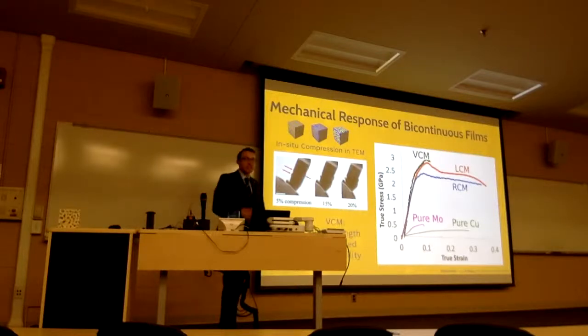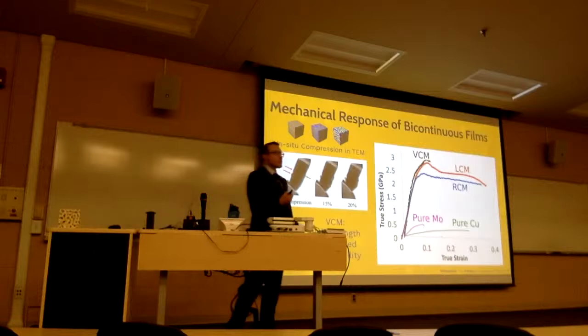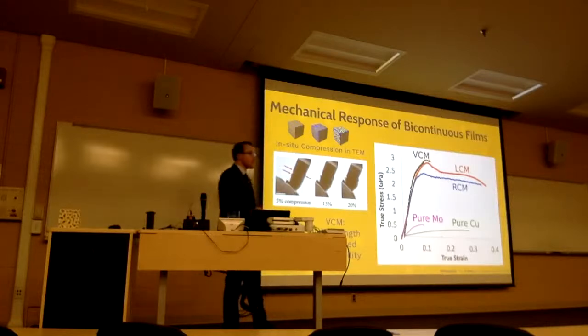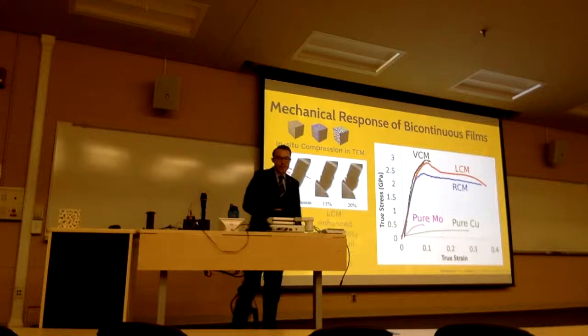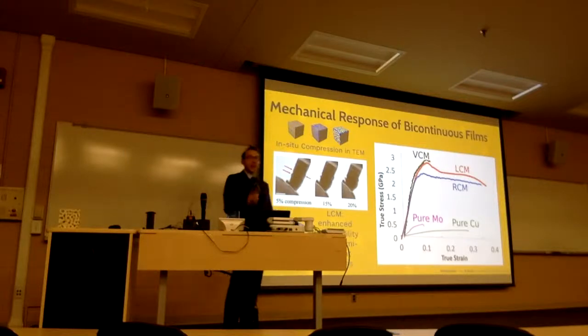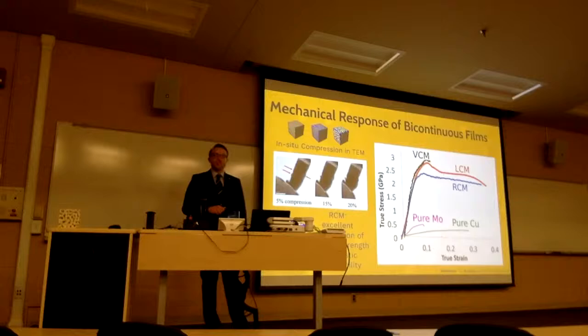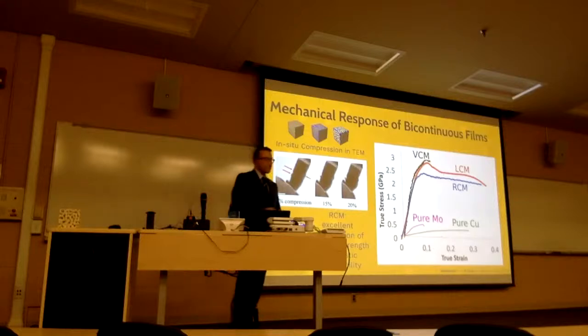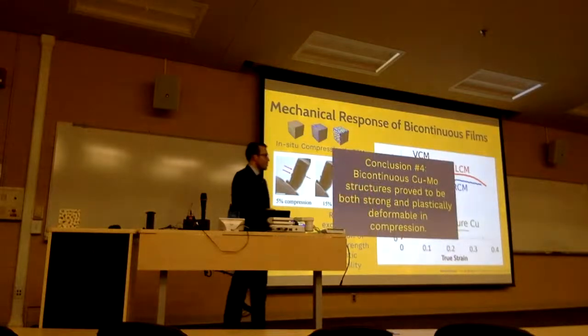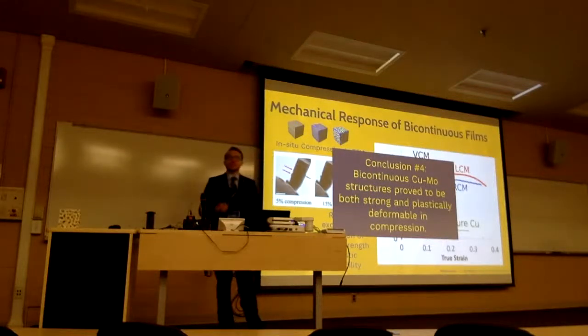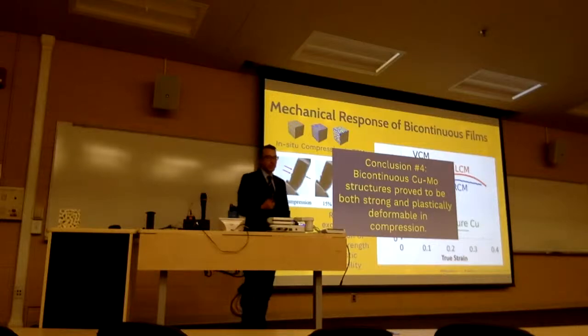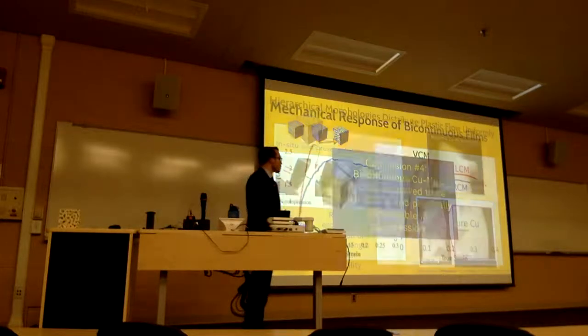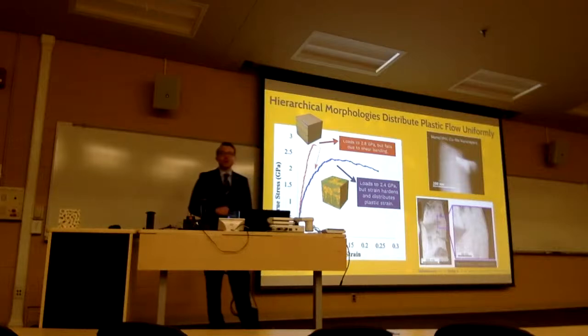What I'd like to highlight is that the VCM structure actually behaved much like a multi-layer-like design, which has high strength but limited deformability. The LCM morphology actually had enhanced deformability due to the presence of semi-coherent interfaces. And finally, the random concentration modulated sample actually had an excellent combination of both high flow strength and plastic deformability. So the conclusion here is that bicontinuous copper moly structures prove to be both strong and plastically deformable in compression. How did the hierarchical morphologies behave?